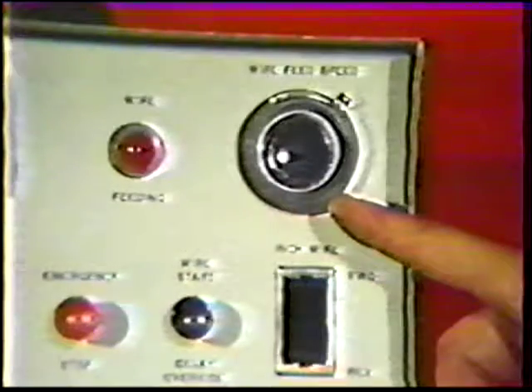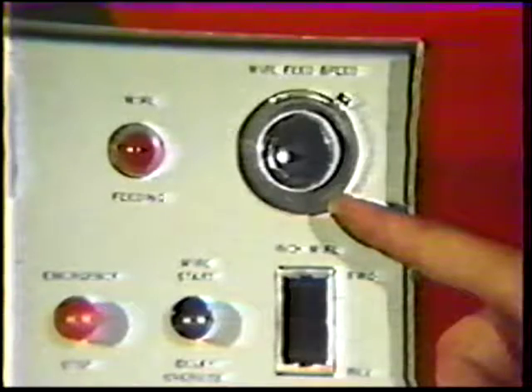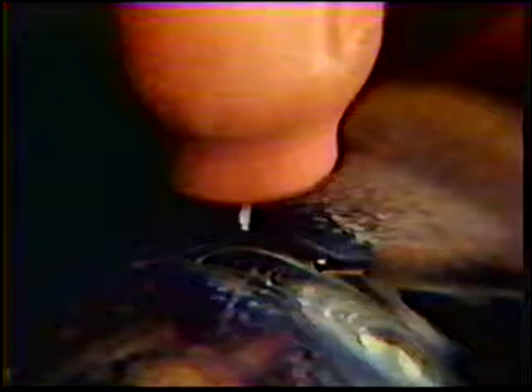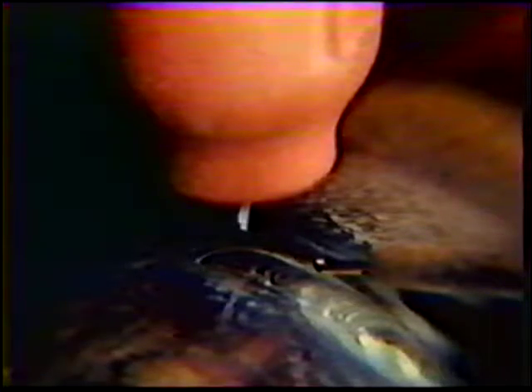The motor speed control also allows for feeding of the filler metal to the arc. This is called cold filler wire addition, since the wire does not carry electrical current. The wire feed speed is adjusted according to the welding procedure variables. Like the control for fixture rotation, the wire feed does not start until the puddle is established.